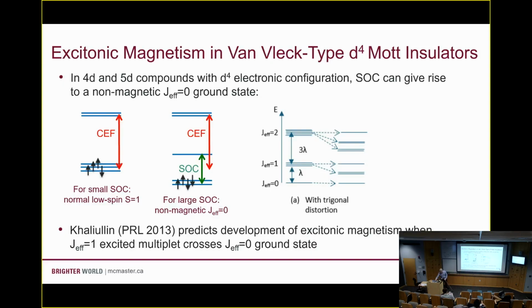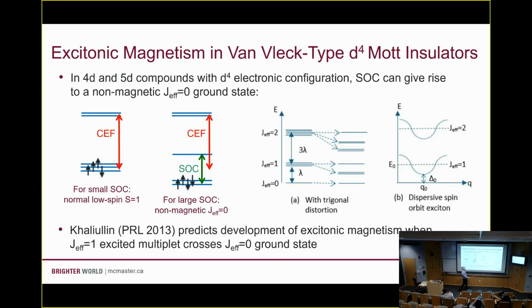You can also do this if you have significant magnetic interactions. So if you pick up dispersion here of this J effective 1 level, we typically call this a spin-orbit exciton. We can bring this down so that the gap becomes small. If this eventually crosses, then we're going to condense and get excitonic magnetic order around this position, Q0.